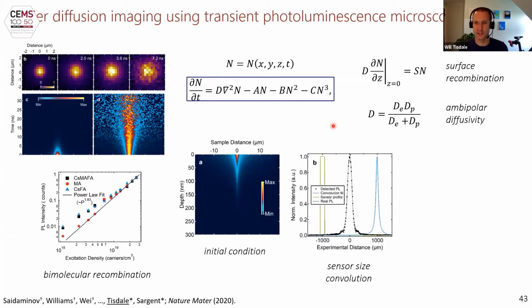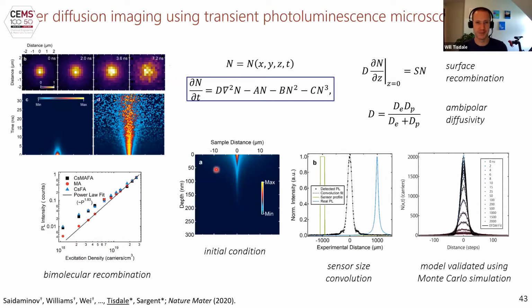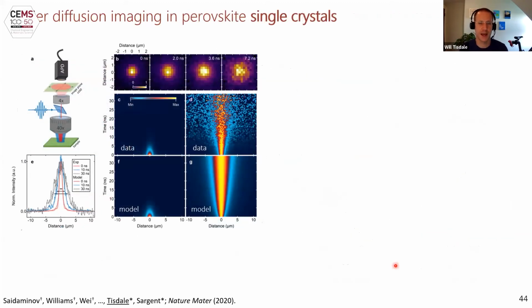This is just more stuff saying we did a very careful job. The initial condition for the simulations is a Gaussian distribution in the surface plane, Beer's law into the sample. We have to take into account the convolution of our detector size with the emission. And then we did a lot of work validating our model using some Monte Carlo simulations and then fitting the Monte Carlo simulations with the PDE solution to develop confidence in our model. Okay, so all of that is the how we did it.